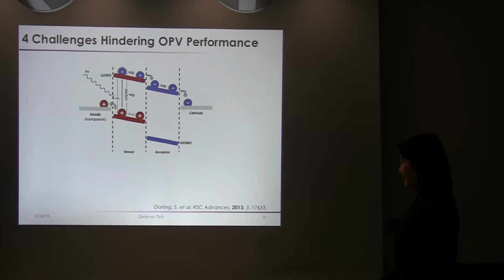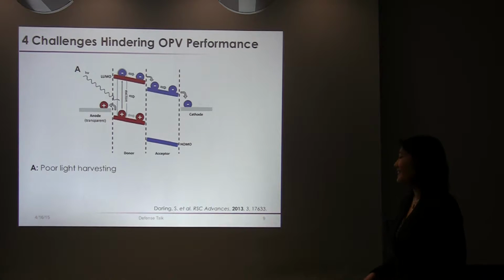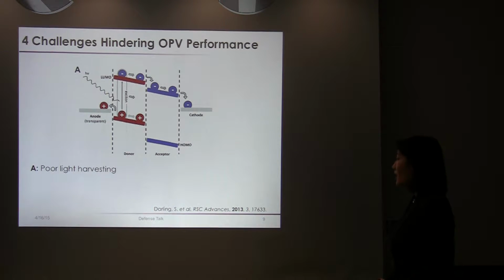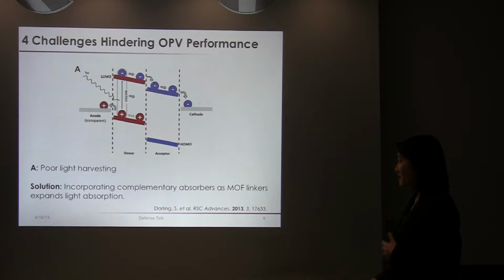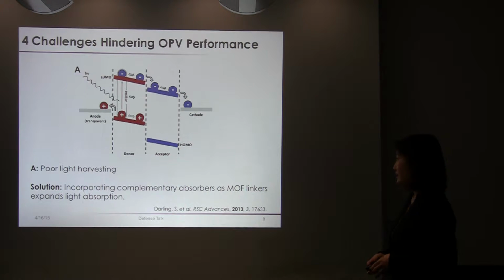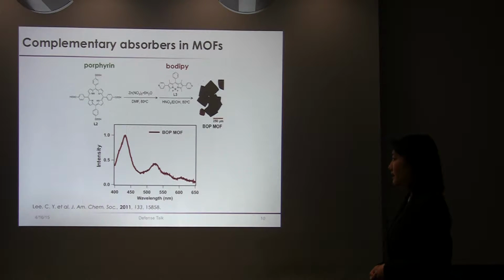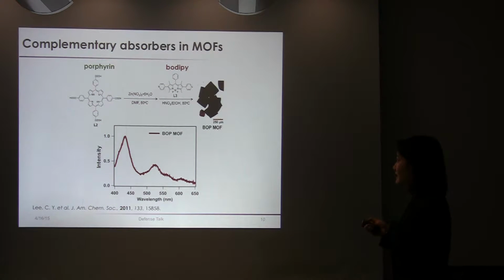So one of the main challenges, as I had mentioned before, with current materials is that there's poor light harvesting. One potential way that MOFs can tackle this problem is by incorporating complementary absorbing linkers into MOFs so that we can potentially expand light absorption. In one of our recent works in 2011, my colleagues combined this tetracarboxyphenylporphyrin linker with zinc nitrate hexahydrate and DMF at 80 degrees Celsius, and then added this boron dipyrromethene derivative that is dipyridyl, that's pyridine functionalized, in an ethanolic solution with nitric acid at 80 degrees Celsius to form these plate-like black MOF crystals.